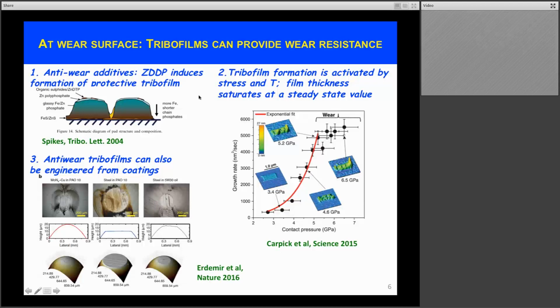Progressively over the last 5-6 decades, the community has developed a good understanding of the origin of this anti-wear property, and it is through the formation of glassy, patchy tribofilms that screen or separate the two bodies and reduce wear drastically. And on point number 2 here, recent work from Carpick and co-workers showed that the formation of this tribofilm is activated by stress and temperature.